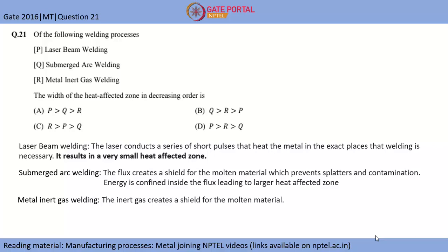And the third one is metal inert gas welding. Here, rather than flux, we use an inert gas such as argon or helium to shield the molten material. Submerged arc welding will have the most heat affected zone, because the heat transfer is not taking place due to the flux shielding the molten material. Hence the heat will be stored in the material only, which creates a large heat affected zone. In laser beam welding it is very localized, hence the heat affected zone is very small, and metal inert gas welding lies in between. So the correct answer is B, where Q is most, then R, then P, where laser beam welding has the least heat affected zone.